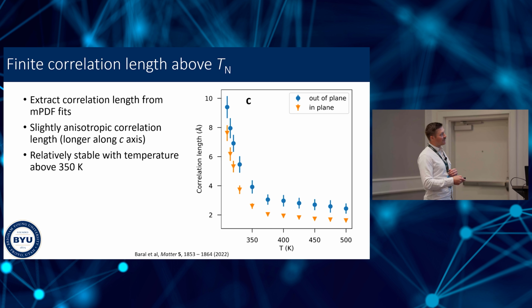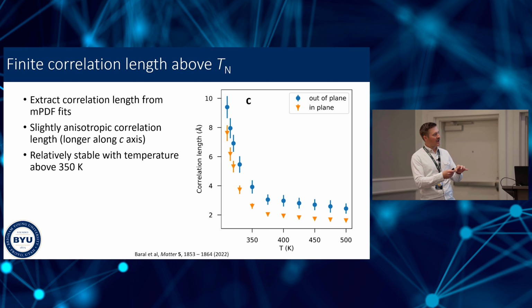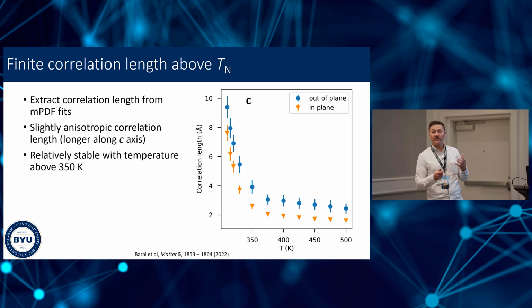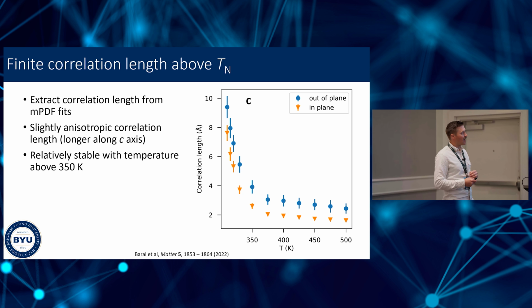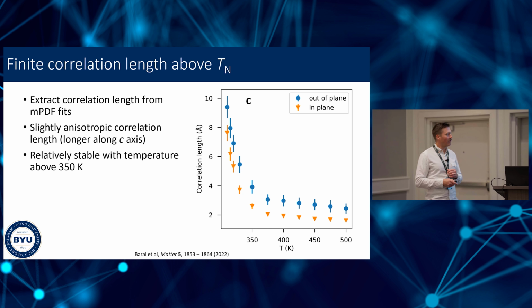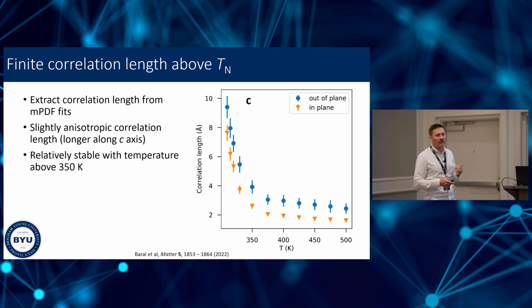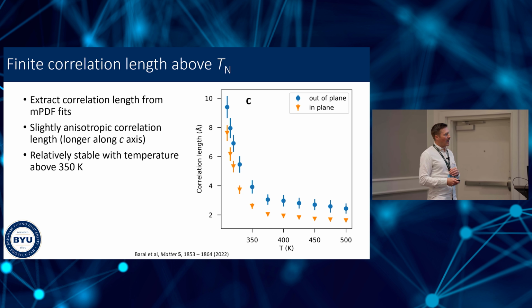It's interesting to note that the out-of-plane correlation length tends to be systematically a bit longer than the in-plane correlation length. It was interesting to me that we were able to observe that even from powder data, where you might think that this directional sensitivity has been lost. But we were actually able to pull that out pretty robustly, and that makes sense in terms of the magnetic exchange interactions in manganese telluride.